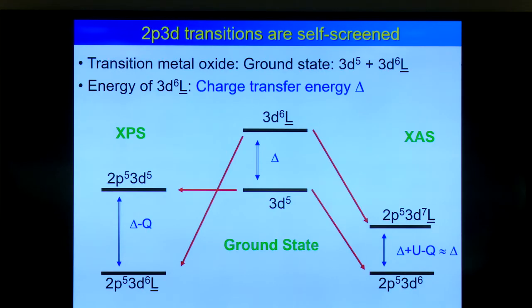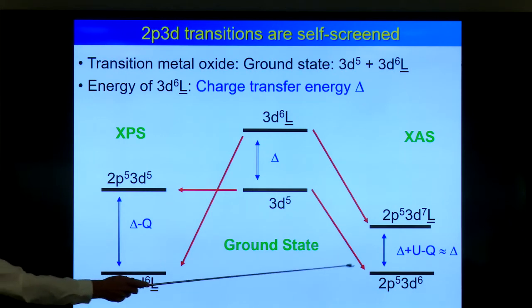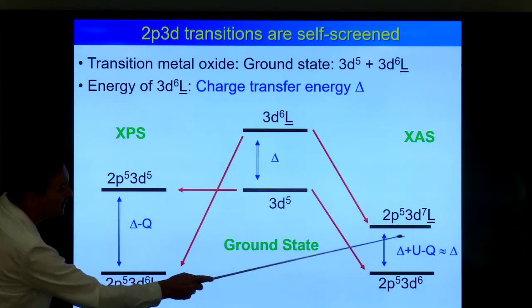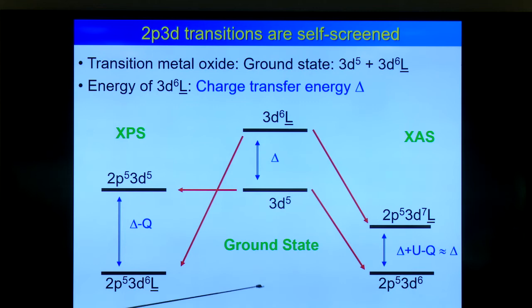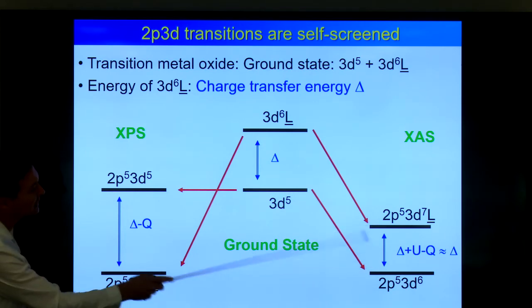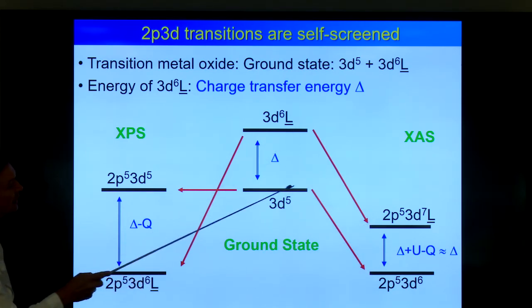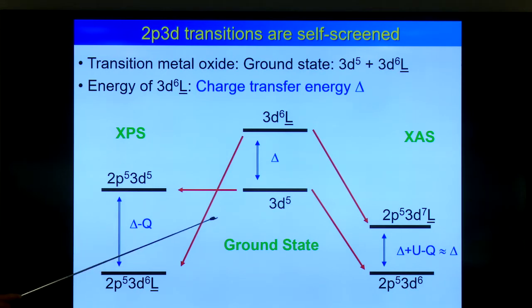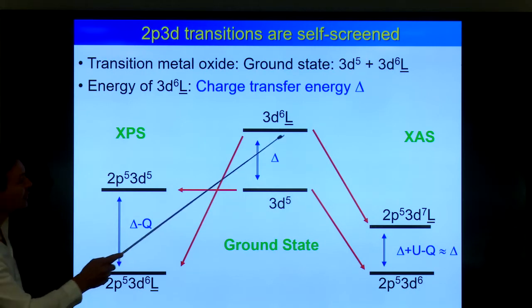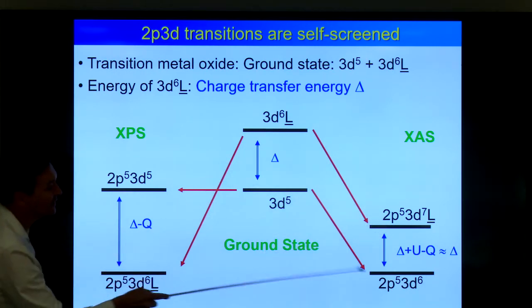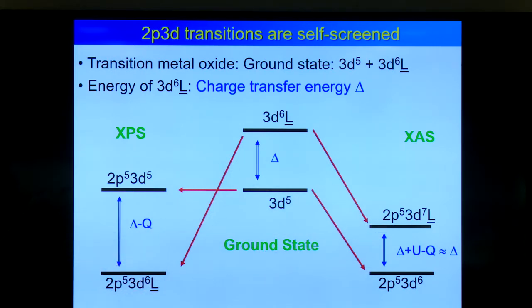And then the two nice experiments to compare are X-ray absorption and photoemission. This is the ground state, d5, d6L. This is X-ray absorption, d6, d7L. If you work out the energetics, you see that the energy ordering of the two states is exactly the same in the final state as in the initial state. So the process of X-ray absorption is self-screened. So you can, in first approximation, neglect this and neglect that, and then you still get a good description. So that's the case for all neutral experiments.